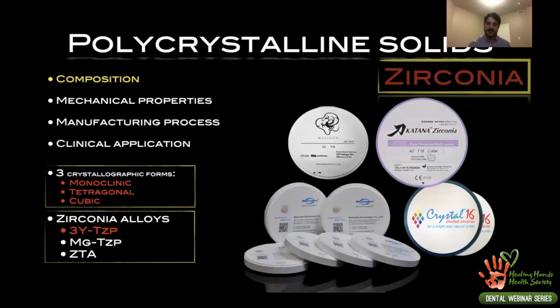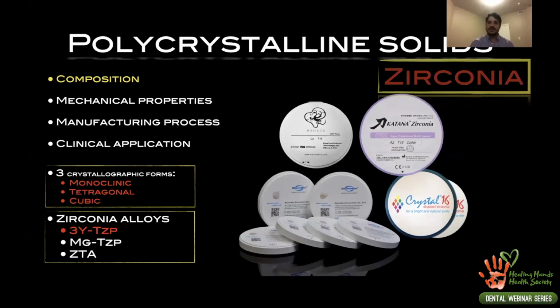And one thing that is extremely important to understand is that zirconia has no patent within the material itself. We don't have a patent for zirconia, similar to what happened with lithium disilicate. Lithium disilicate is known in the world as Emax because Emax held the patent for lithium disilicate for a long time. Zirconia has no patent within the material, which means that you can have, and literally you have, 200 different zirconias. That's why it's important for you to understand the crystallographic, mechanical and optical properties of the material, so you can select the specific one that you know is going to behave predictably the way that you want.